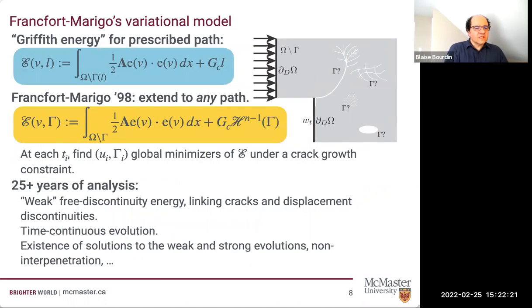So what can we do instead? Well, in the mid-90s, the math community became really enamored with so-called free discontinuity problems, and many of them came from the image processing community. But the idea was to apply this theory to Griffith's fracture, and in particular, Francfort and Marigo in '98 in France really proposed to do the following. Instead of postulating the crack path and minimizing the so-called Griffith energy, why don't we take the energy for what it is, the sum of the mechanical energy plus Gc times the length of the crack, and minimize it with respect to what? With respect to any admissible displacement and any crack set.